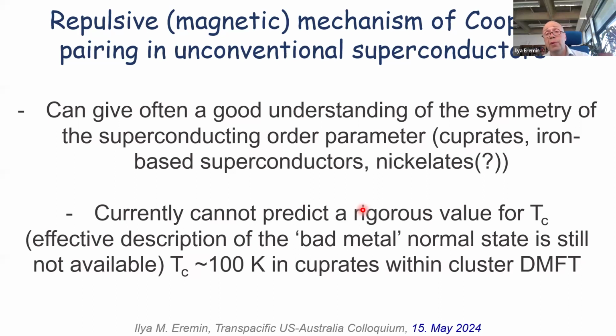Also, because in many of these systems there are different symmetries competing for winning the Fermi surface, you can have an S-wave, extended S-wave order parameter realized, but the D-wave will be subdominant, and then you can have a Bardasis-Schrieffer mode. If you compute the fluctuation spectrum in the superconductor, it's extremely broad, and there has been experimental identification that such modes were observed.